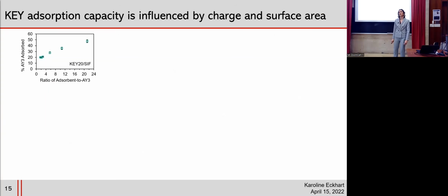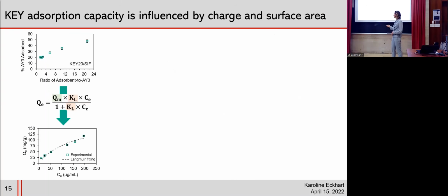We next wanted to quantify the adsorption capacity of these systems. So we measured the % adsorbed at different ratios of the adsorbent to the adsorbate. And then we rearranged this data to form a graph looking at the adsorption capacity at equilibrium. So this is the milligrams of drug adsorbed per gram of adsorbent versus the concentration at equilibrium. This is the concentration of drug that didn't get adsorbed after equilibrium was reached.